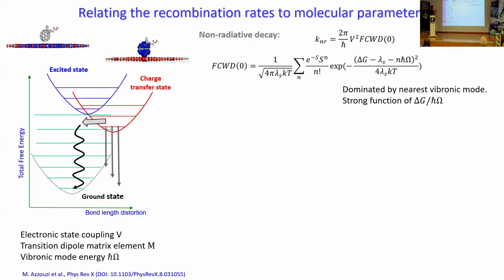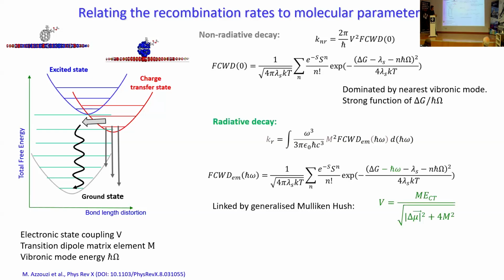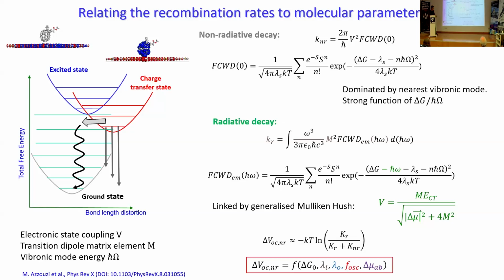We can describe these processes quite well using tools from physical chemistry, where we look at this transition between the excited state and the ground state. And we describe the rates with Marcus-Levich-Jortner, sort of semi-classical rate theory. And the point is, we can write down the rate of non-radiative and radiative recombination and work out the ratio between them, and then work out what this open circuit voltage loss should be.